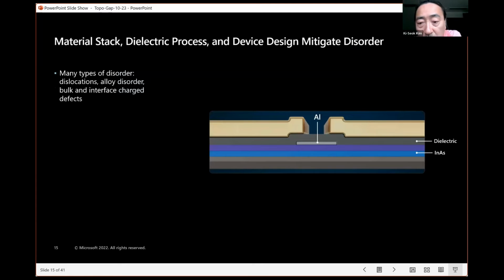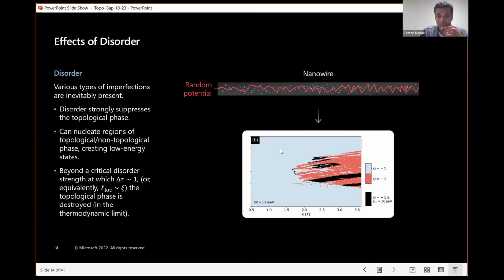What is the black region? This region here? Black. Yeah. Black is when it's topological and the gap exceeds the minimum value of 10 microvolts. So it's topological with a sufficiently large energy gap. And that's a pretty low threshold, only 10 microvolts. So it's really saying all this other red region is technically topological, but the gap is very small. It's less than 10 microvolts in this red region. The black region, these fragments, that's where you have, you could say, a topological phase with at least a non-negligible energy gap.